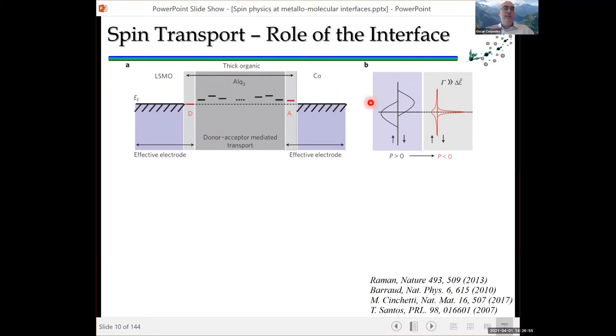And this is what Stefanos and Vito from Trinity coined as the spin interface. The fact that you put your molecule on top of the metal, and the charge transfer, the rehybridization is going to broaden the molecular orbitals, and it might also shift them according to spin. So then you are going to have a different behavior depending on what you have at that interface.